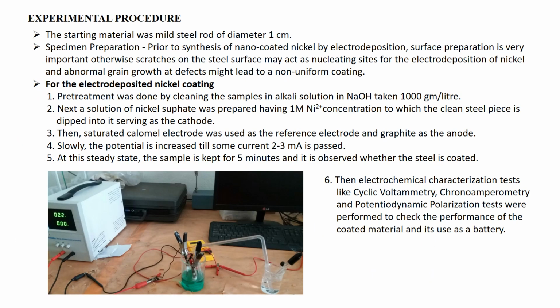Now, experimental procedure. The starting material used was mild steel rod of diameter 1 centimeter. Before this, we need to take care of the surface preparation. Otherwise, there may be nucleating sites which may lead to a non-uniform coating, and this arises mainly from scratches on the surface. So, pre-treatment is done by cleaning the samples in alkali solution.